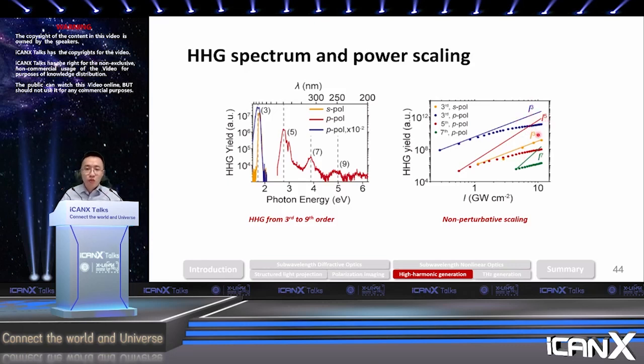What we feel is the biggest advantage of this device is that, unlike typical gas or solid phase high harmonic generation, which often requires a peak pump intensity on the order of terawatt per centimeter squared, in this case, due to the enhancement of the ENZ effect, we only require a pump intensity on the order of 10 gigawatt per centimeter squared to get this nice harmonic generation, which is 2 orders of magnitude improvement.